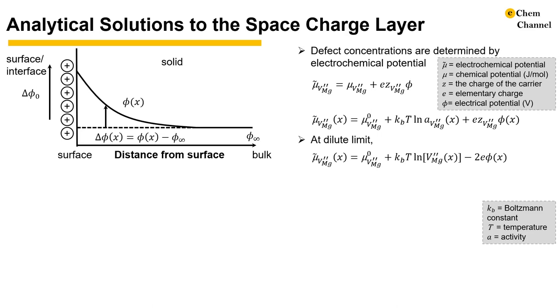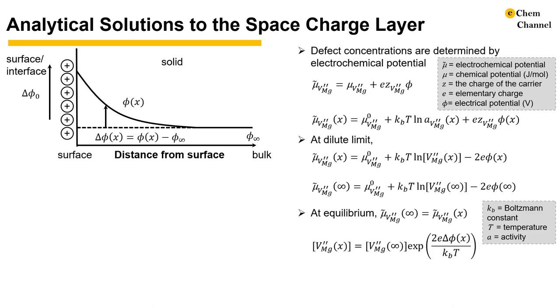Also, we know that the vacancy at magnesium sites carry two negative charges, hence we have an updated equation like this. In the bulk, this equation still holds true. Assuming we are at electrochemical equilibrium conditions, the electrochemical potentials near the surface will be the same as in the bulk. By rearranging the equations, we get the equation for the concentration of vacancies on magnesium sites.